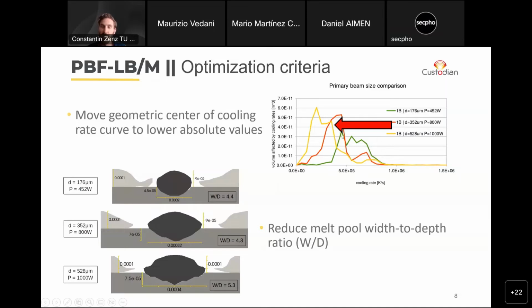And we can see how the vast part of material is then experiencing lower cooling rates. So by shifting these curves to the left, this means more material is actually affected by lower cooling rates. And so we can quickly compare different configurations. If we have several sets of laser parameters or beam shapes, we benchmark them against each other by comparing these cooling rate plots, because the ultimate goal is to reduce cooling rates in this critical temperature range that we just heard about in the previous talk.